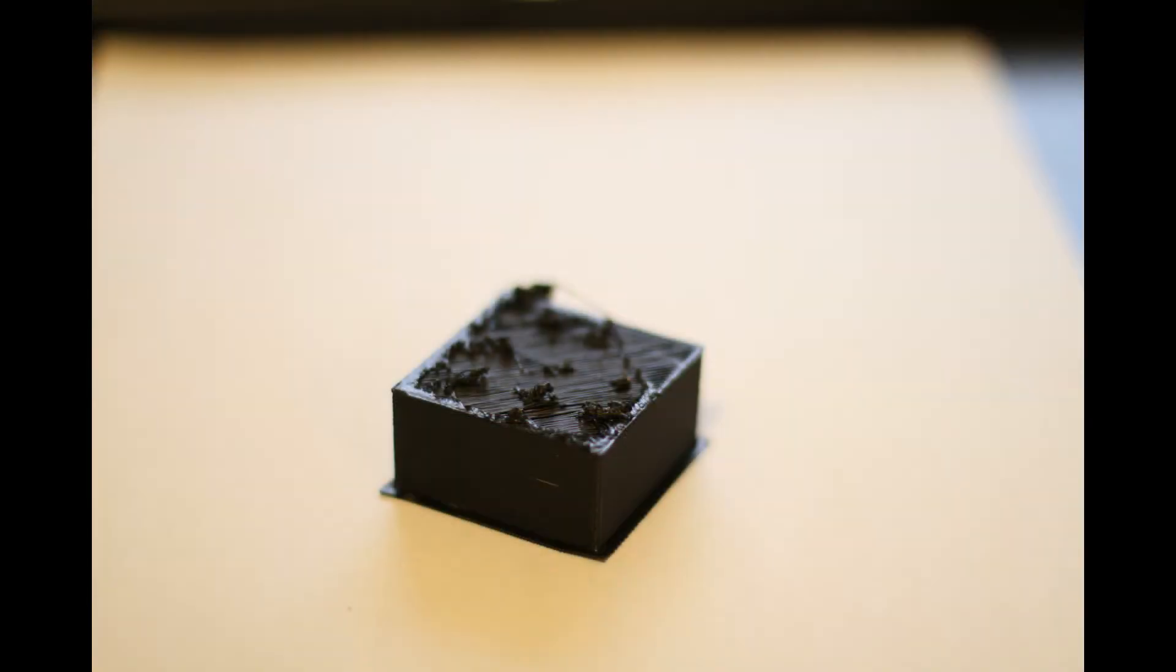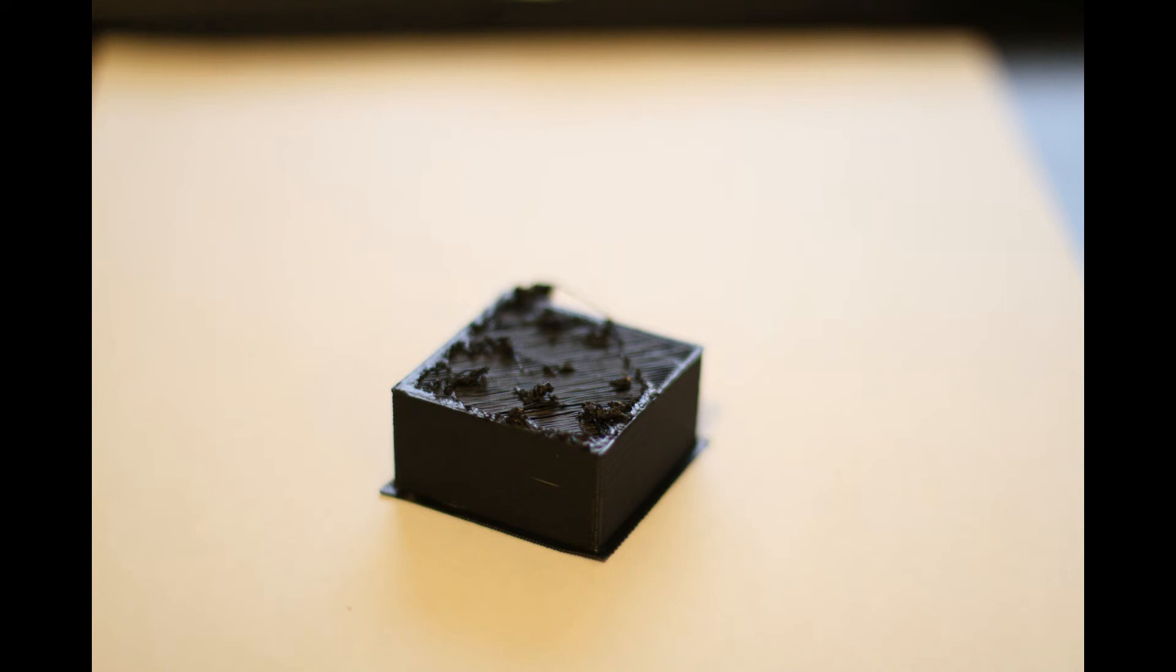In this picture we can see that the last layer, the top layer, wasn't laid out correctly and instead we have these clumps of plastic. This is because you either have the layer height set incorrectly, your printer print head has some stuff stuck to it so the printed filament gets stuck to the print head and gets dragged around, or you're not printing fast enough in the last layer. Try increasing the print speed on the top layer and it might solve the problem entirely.